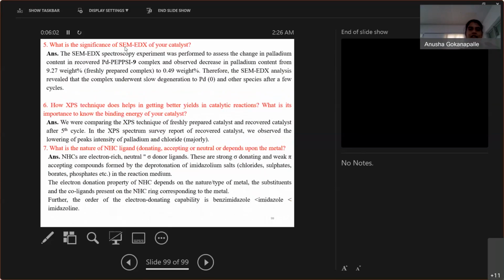What is the significance of SEM-EDX of your catalyst? SEM-EDX spectroscopy experiments were performed for recovered palladium PEPPSI complexes, and a decrease in palladium content from 9.27 to 0.49 weight% was observed. For this purpose, we used SEM-EDX